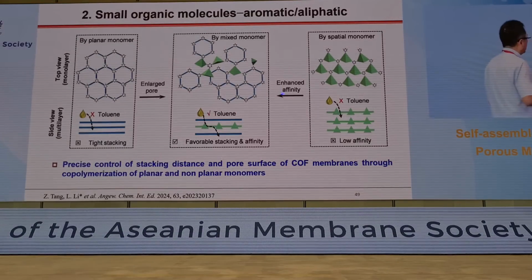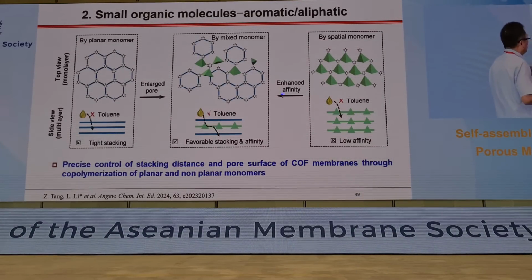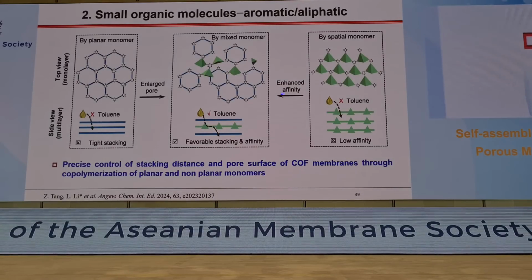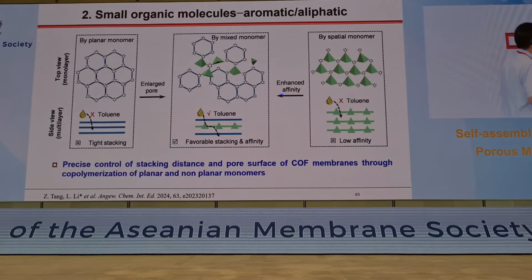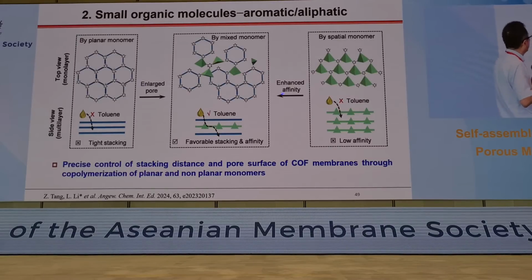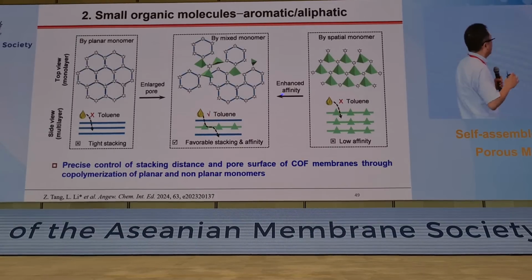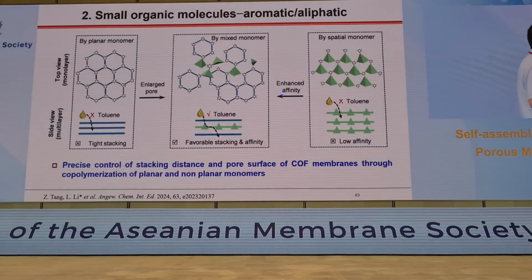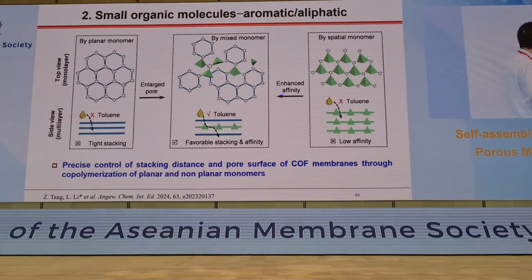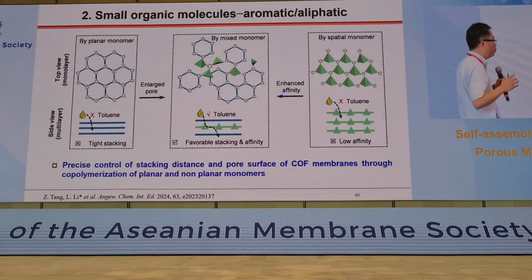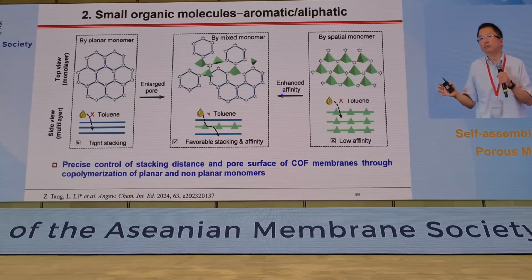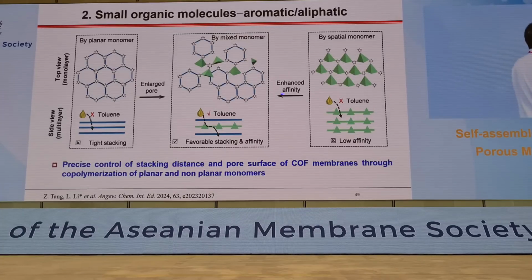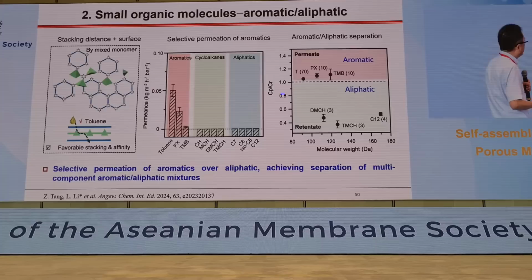We further wanted to tune the stacking distance and the pore surface property of the membrane through the polymerization of planar and non-planar monomers. We found that after introduction of non-planar monomers in the two-dimensional membranes, we successfully tuned the interlayer spacings.